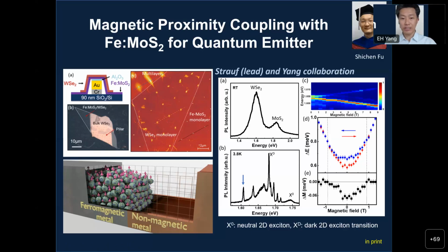Let's go to the right side. Figure A is photoluminescence from tungsten diselenide, and figure B is focused into the 1.6 to 1.75 region, at 3.8 K. And you see these sharp spectral peaks here. X0 is the neutral exciton, XD is the dark exciton, but this one is your quantum emitter.